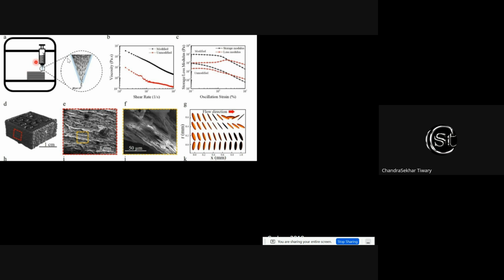And what we are showing here, the first thing we did, was 3D print graphene. So we took graphene, made it into ink, and then we tuned the rheology with a binder and other additives such that we can make a nice extruded structure. If you can do that, you can see here we have printed a complex shape where we have a high surface area. The scanning electron microscopy shows that these layers are intact and nicely aligned. Once we do a simple treatment to get rid of additives, we retain the carbon structure, which has good strength and a good amount of ductility.